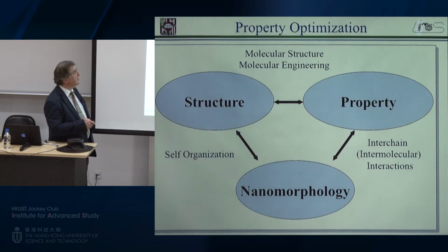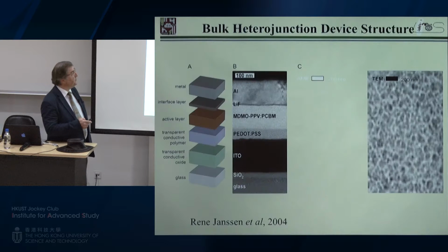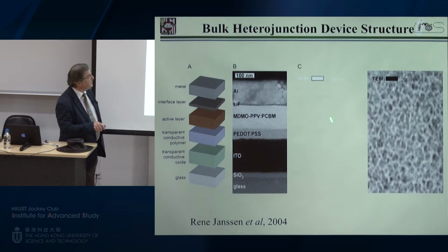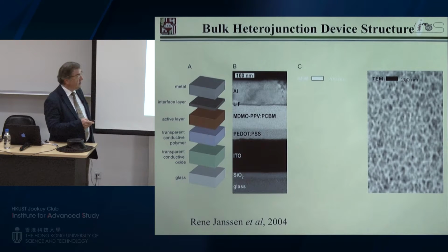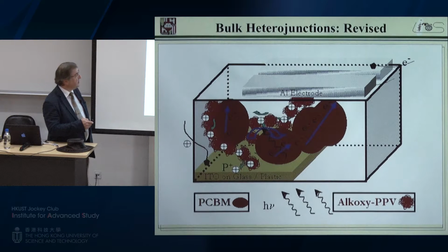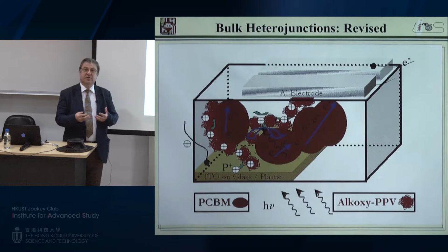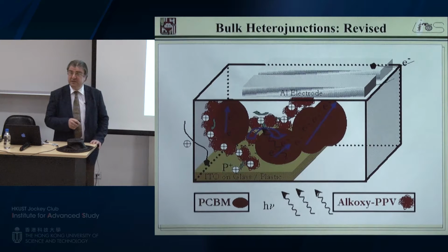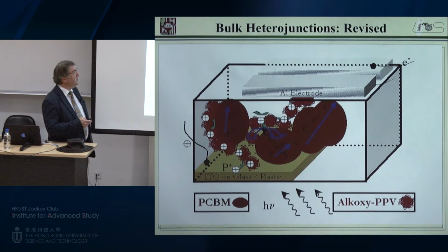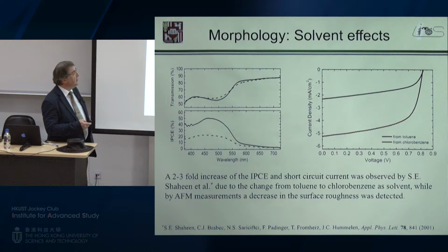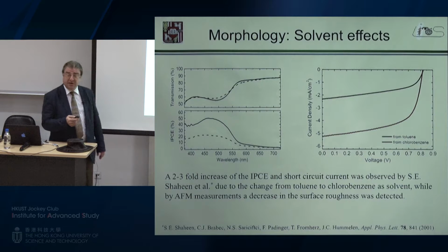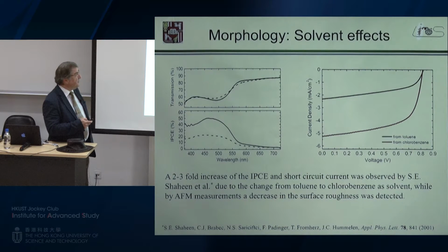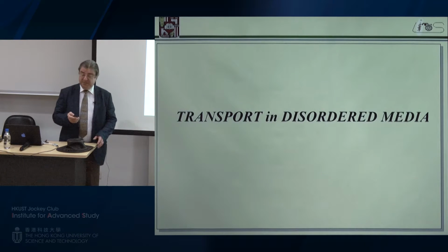The third one is this structure-nanomorphology relationship. If we look at the nanostructure, and there is one picture missing here somehow, this is a mixture which demixes itself by spontaneous phase segregation, which leads to an enormously disordered structure. If we cartoonize this picture, we have a wild and disordered mixture of nanoparticles of donors embedded into the nanoparticles of acceptors. That doesn't seem to be a very nice physical system. And indeed, if you just change the solvent, for example, absorption doesn't change, but the solar cell efficiency can be increased manifold. So how does this come about? This is basically the theory of another Nobel Prize fellow,